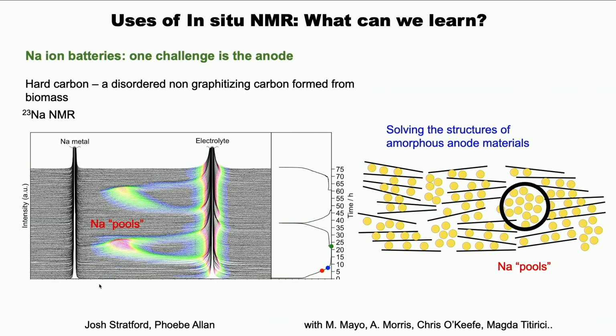And so what we did was to use sodium NMR to understand the mechanism of how you intercalate or insert into these hard carbon, graphitic-type structures. The model of a hard carbon is the so-called house of cards. And what we showed was that you had, first of all, insertion into diamagnetic regions, and then you filled in these so-called sodium pools within the pores inside the hard carbon structures.